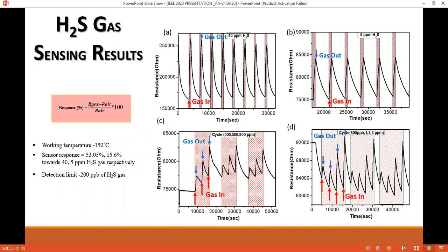The four graphs here show the gas sensing characteristics of the fabricated sensor towards different concentrations of H2S gas at a constant operating temperature of 150 degrees Celsius. When the sensor is exposed to H2S, which is a reducing type of gas, the resistance of the device increases, which indicates that our fabricated sensor behaves as a p-type semiconductor.